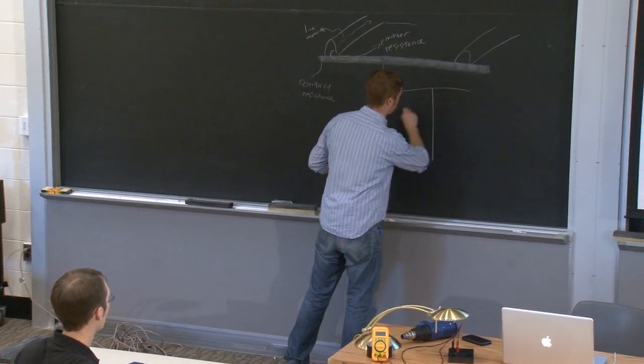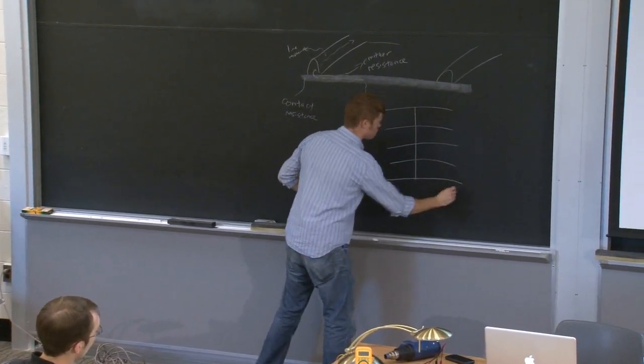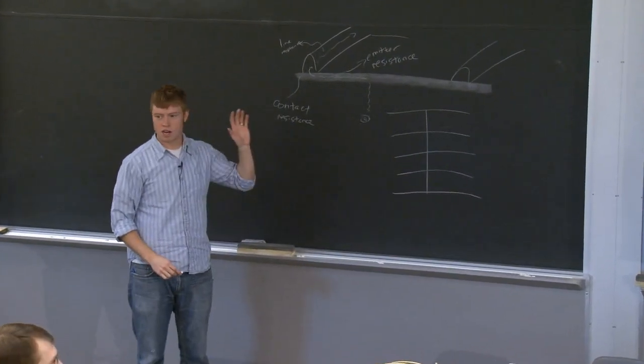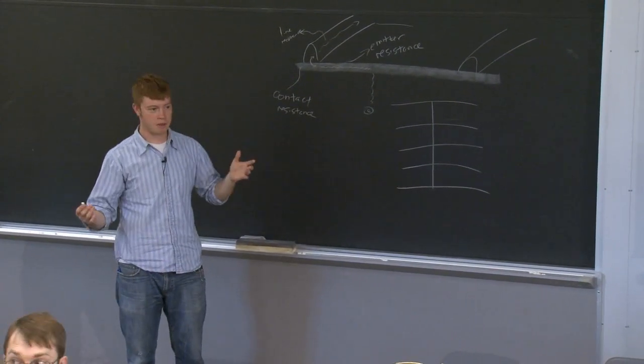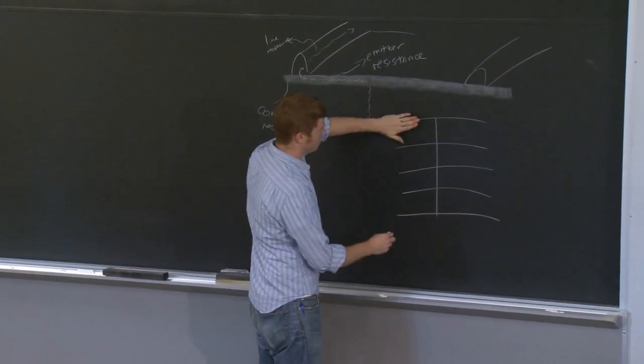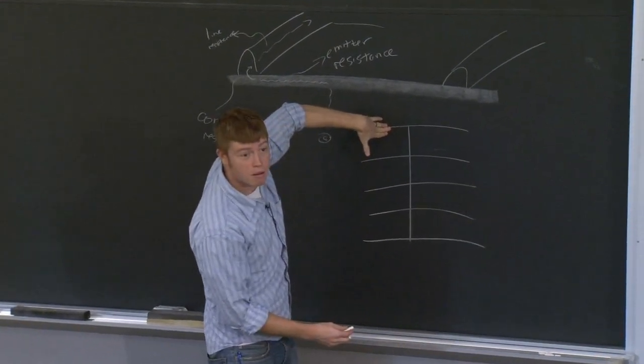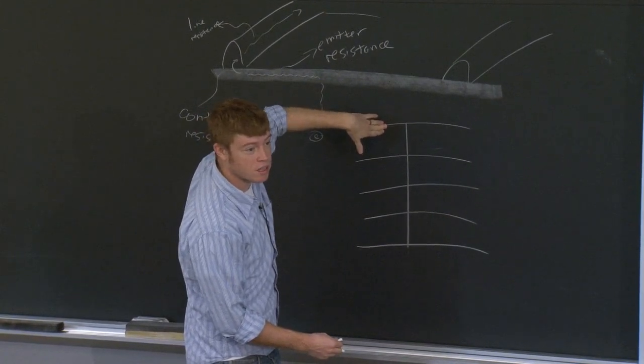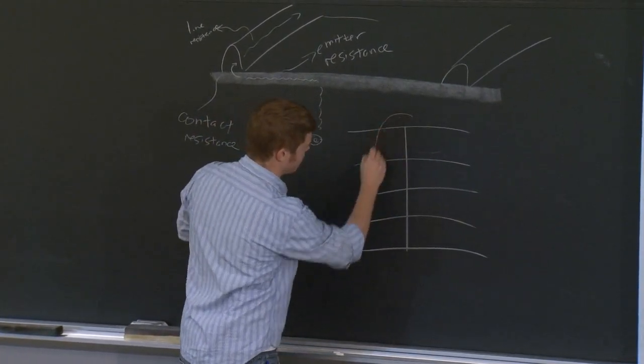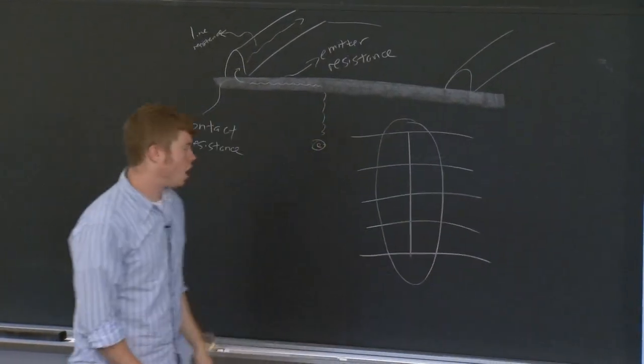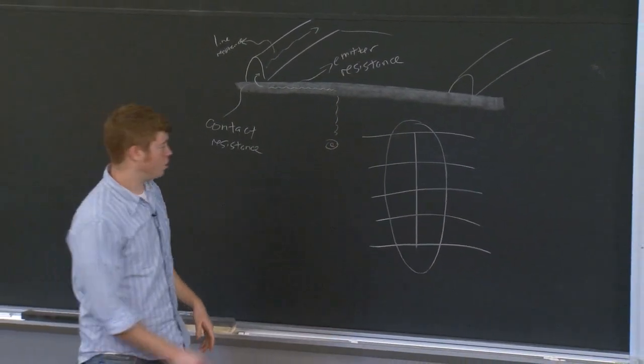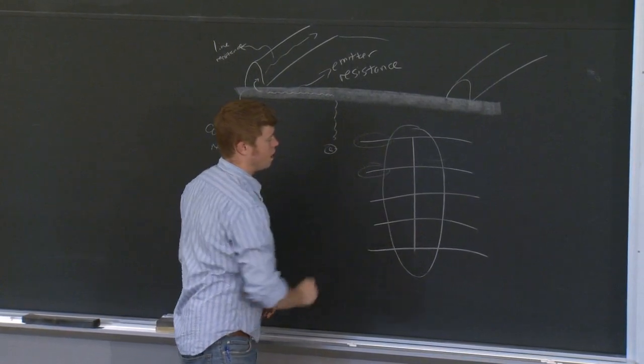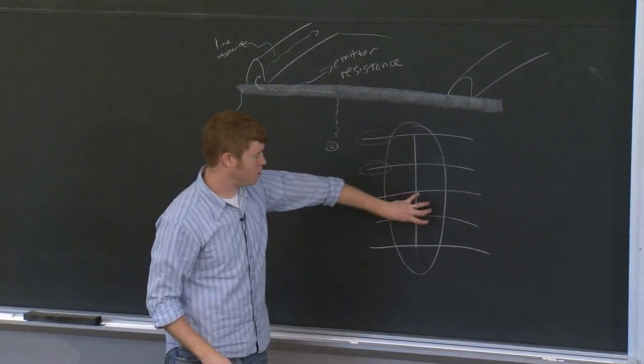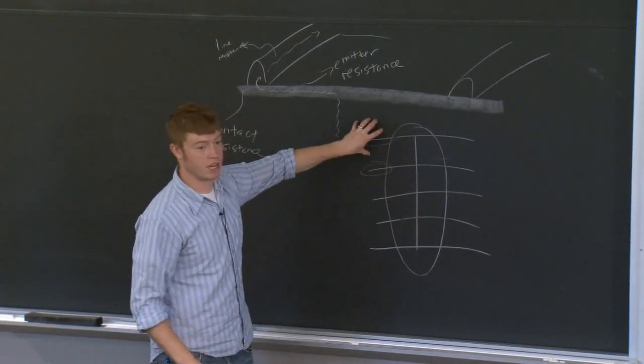Right, here's our bus bar. Some people saw delamination. Who saw their contacts delaminate? Yeah, so a couple people. What that means is that these contacts actually peeled up. What's funny though is that these areas in the middle didn't delaminate. It was only the edges here. That's showing that some parts are being properly fired and some parts are being underfired.